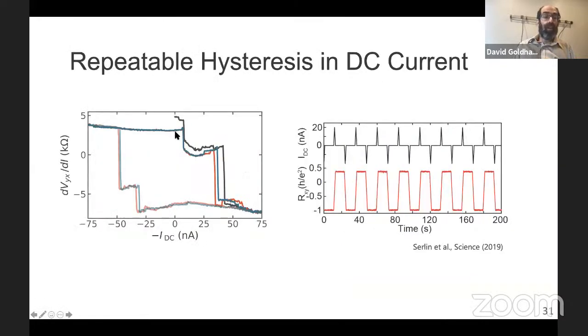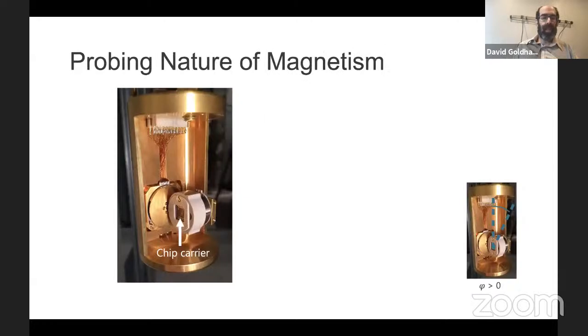So there are other striking things here. For example, we accidentally discovered, by being too greedy and running too high a current in our lock-in measurements, that we lost our signal. And then we started trying to just drive a DC current through the sample. And we found that without any magnetic field, we could flip the magnet just by driving tens of nanoamps in one direction. And then we could flip it back with a current in the opposite direction. And Andrea Young's group verified this, that they could flip their magnet back and forth too. There are a couple of different theories for how this can happen, but I would say it's not really fully explored and answered. And so let me now just say we've been trying to understand what this magnet is.